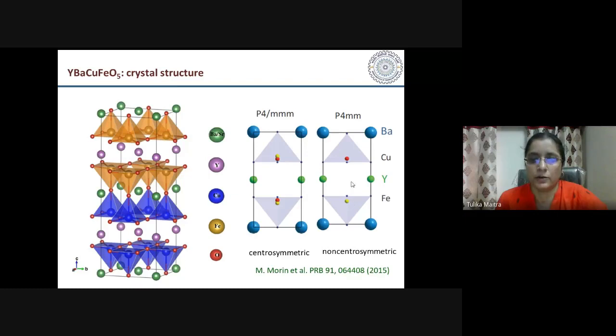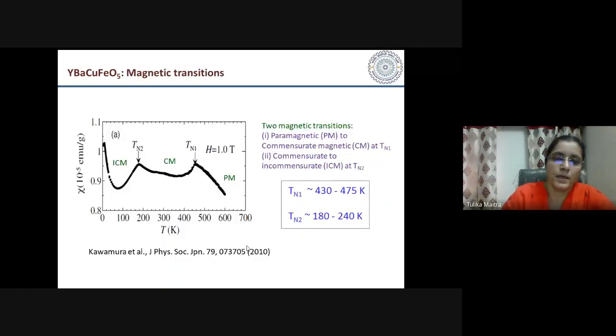Okay, iron and copper are separated. Both these space groups are claimed to be fitting the experiments. So this compound undergoes two magnetic transitions. One is from paramagnetic to commensurate magnetic state at Tn1, and then from commensurate to incommensurate state. Okay, and so these are the two transition temperatures.